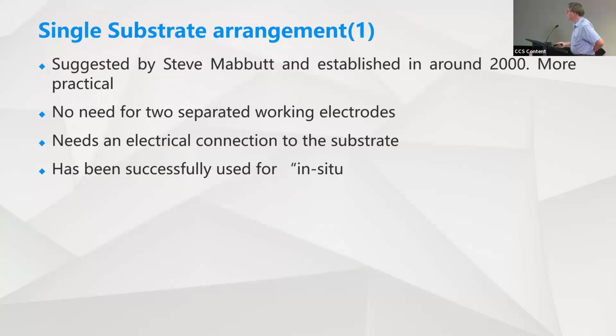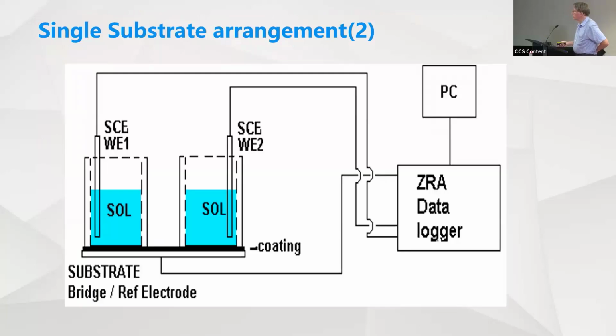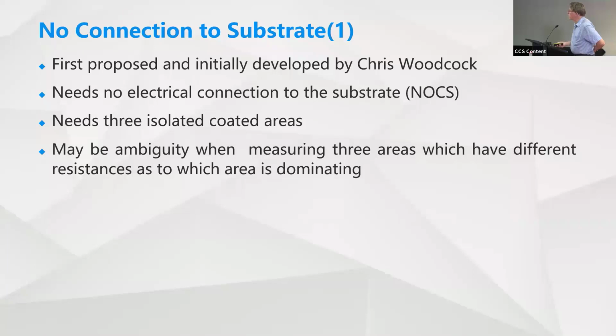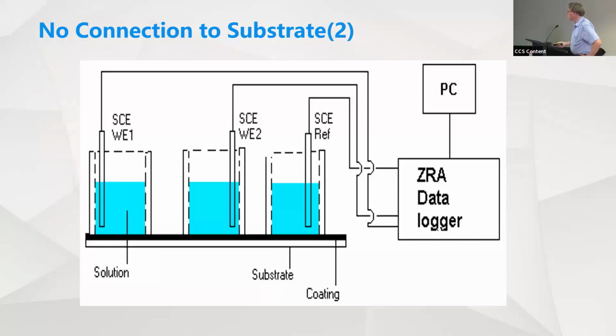And this is the new-ish, well, not that new, arrangement that enables you to do it on just one substrate, by jigging things around a bit. And of course, what we had to do was show this was equivalent to the bridge, which it proved to be. And then we have this arrangement with no connection to the substrate, which is obviously good, since having to cut out the coating to make a connection onto the metal is obviously unattractive. So that was an advantage of this arrangement, which looks a bit like that. And again, work we did showed that this was getting similar results to what you would have got with the bridge.